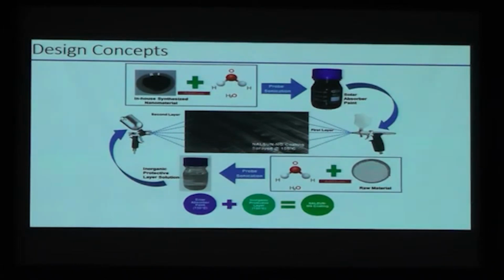For the absorber layer, we have mainly used graphene oxide as the base material, and we have used water as a solvent. We have added a few other additives, and we made this coating as an absorber coating. Generally, graphene oxide is a black body absorber. That means whatever it is absorbing, it will emit everything. Whereas what we have done is that by adding a few additives, we converted this black body absorber into a spectrally selective paint. And the second one is the inorganic protective layer solution.